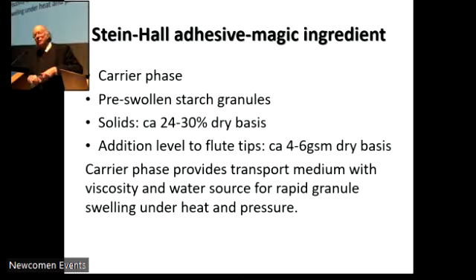The answer came in the form of a thing called the Stein-Hall formulation, which sounds like the title of a detective thriller or spy thriller. It's actually deceptively simple. You have a carrier phase made of totally dissolved starch, which is a bit like wallpaper glue. And into that you disperse some pre-swollen starch granules. If you apply heat and moisture to starch, it will swell. And the solids content in total is about 24 to 30% dry basis. The addition level to the flute tips over the board is about 4 to 6 grams per square meter. So you're not putting an awful lot on.